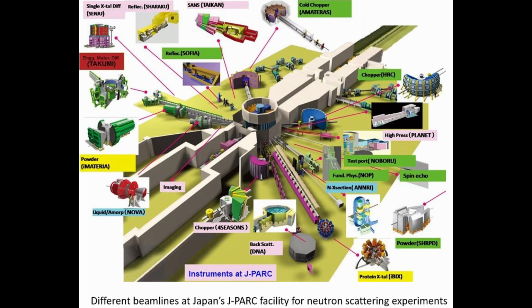With neutrons, for example, with steels and high entropy alloys, we can use 5-6 millimeter thick samples. So we can really gauge millions of grains or maybe more, and we can have a very big beam. In that way, we can really look at the bulk behavior. And also in situ: when you're cooling, you're measuring your data constantly. Similarly, when you're tensile loading, you're straining the sample, so again you're collecting data continuously, so you know really what is happening.